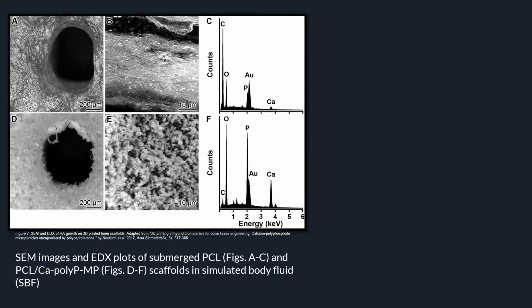After depositing PCl and PCl calcium poly-P scaffolds into simulated body fluid for 4 weeks, the researchers used energy dispersive X-ray analysis, SEM, and FT-IR spectroscopy analysis to determine the mineral growth of HA on the scaffolds. Hydroxyapatite, or HA, is a major constituent of hard tissue, such as bone and teeth, and is therefore desirable for implant coating. Previous research has shown a 1.6 calcium to phosphate ratio is needed for HA development.